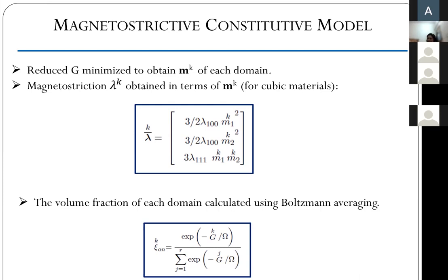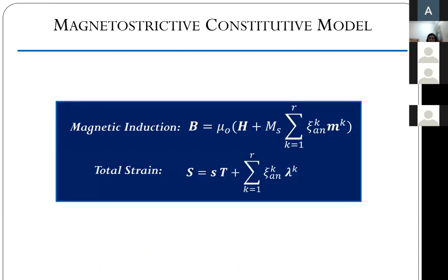Again, something that I have skipped over, I have not talked about, but that comes in through this term. The volume fraction is calculated through what's called Boltzmann averaging. Then we sum up the entire response in this manner. We calculate the magnetization, as I mentioned before, by doing this local linearization and then minimizing the energy. That gives us all the magnetic moment orientations of each domain, and then we sum up. We calculate the domain volume fraction using the statistical mechanics based averaging, and MS is a known constant.